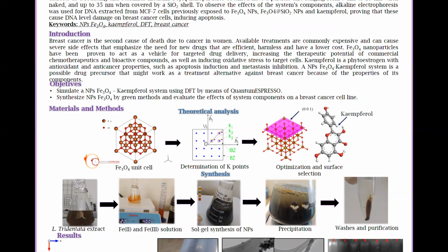And now for the materials and methods. For the theoretical methodology, density functional theory calculations were made with plane waves by means of the software Quantum Espresso. Such calculations allow us to determine how feasible it is to obtain a magnetite nanoparticles KAEMPFEROL system. Therefore, with the relaxation of the magnetite structure in bulk, an LDA+U pseudopotential was employed with a U of 4.5 electron volts and a polarized spin.